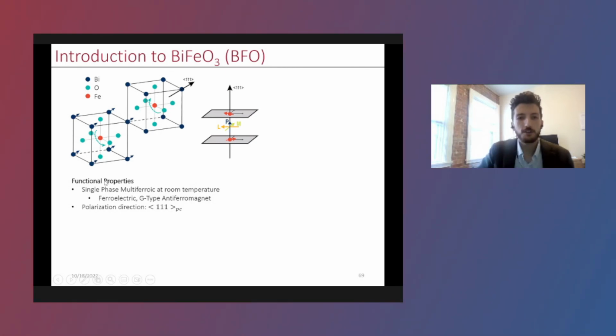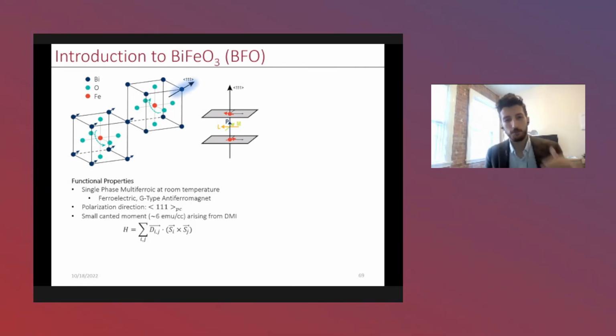So the ferroelectric polarization actually points along the 111 direction, or the pseudo-cubic diagonal, and it's a G-type antiferromagnet. So in fact, hematite is actually the parent compound of BFO. So they have very similar magnetic structures. It's a G-type antiferromagnet, and it does also have a small canted moment, which arises from the DMI, on the order of 6 emu per cc.